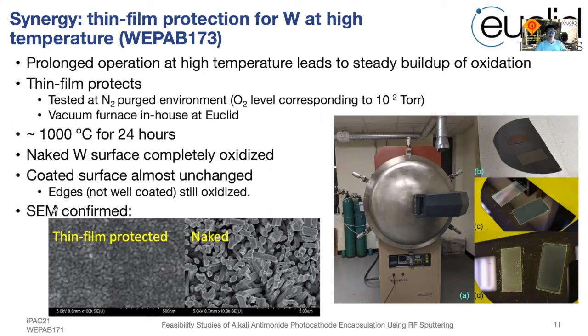In order to protect the tungsten target for high energy physics experiments, which will run the tungsten target at high elevated temperature for prolonged operation, we use the thin film to protect the tungsten from oxidation. In this study, we have used our in-house nitrogen purged high temperature furnace and a silicon dioxide thin film coated tungsten wafer and a regular naked tungsten wafer. After some heating treatment, we inspected it under the SEM. This heating was done for 24 hours at 1000 degrees C approximately.